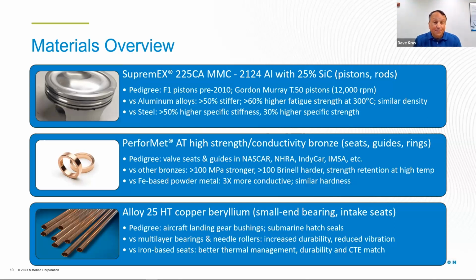Our PerforMet alloy is a copper alloy, kind of call it alloy soup: copper, nickel, silicon, chromium, zirconium. It's used in valve seats and valve guides in a lot of racing classes. It's more popular in North America than it is in Asia or Europe. But compared to most other bronzes, other than the copper beryllium below it, it's a lot stronger, it's a lot harder, and even more so than the copper beryllium, it holds its strength at a high temperature. It also has very good thermal conductivity, so it can move the heat away from, for example, the valve head, or distribute it around, away from the hot spots in the head.